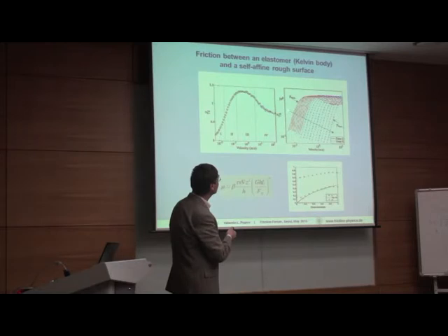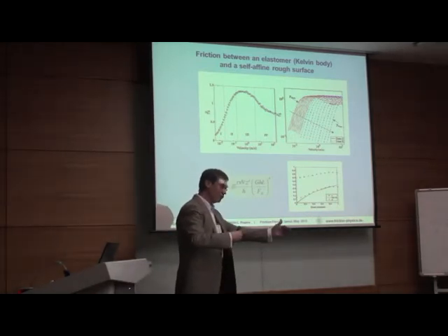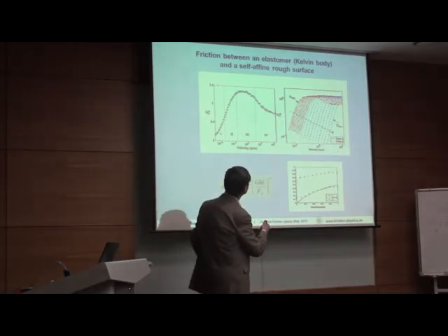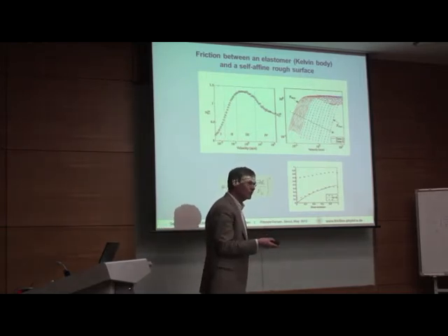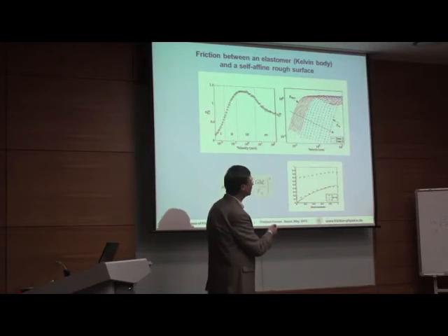This is the dependence for different forces. The same dependence as a function of velocity, but for small forces, you see that in this interval of forces it is logarithmic or exponential increasing. So you see that this is some linear dependence, but on the logarithm of force, and here it is a double logarithm: the logarithm of mu and the logarithm of velocity. And then again some power dependence, but with another alpha at small forces and larger forces.